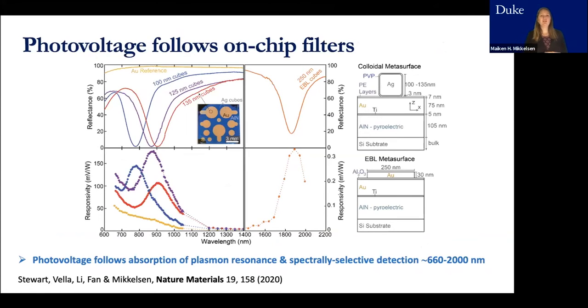So first we wanted to see if these spectral filters actually work, if you can actually control which wavelengths of light are detected by just changing the size of the cubes on top. And what we see is that the photovoltage does indeed follow these spectral filters. So the top here is showing the reflectance spectrum, indicating the plasmon resonance of 4 different structures. So we used 100 nanometer cubes, 125, 135.